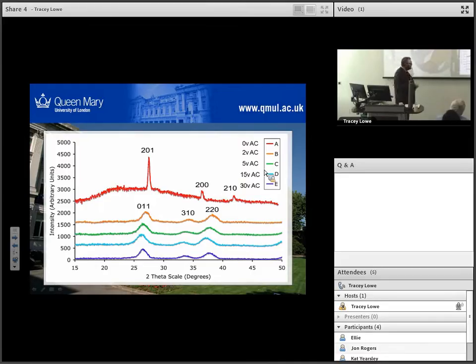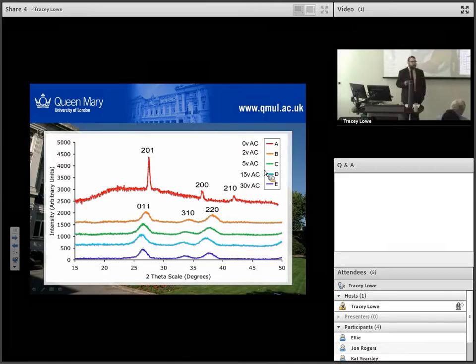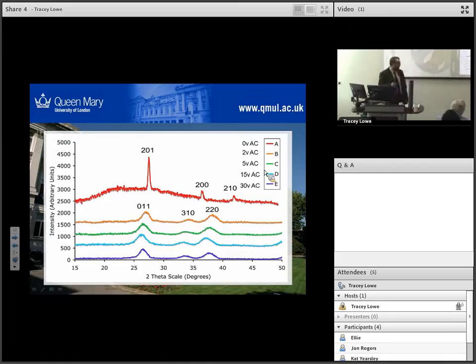Unfortunately, we don't get enough peaks in our X-ray diffraction to make any significant claims about how the cell volume or lattice parameters are changing, other than to say a shift towards zero would tend to indicate a larger unit cell. But we can't really say that with any confidence because we don't have enough peaks for a meaningful calculation. Anyway, things are changing based on the application of these electric fields.